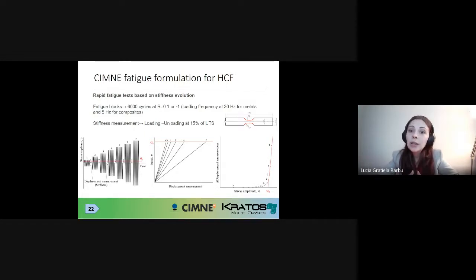And after each of these loading blocks, they do a loading and unloading of that specific specimen at 15% of the ultimate tensile strength. This is done to detect the change in stiffness inside the material. You can see here, for instance, that the loading history for this type of test has a progressively higher stress amplitude applied on the specimen. As you finish a block and then check this change in the stiffness, you can see here that the displacement measurement varies after each load. So if you quantify this change in the displacement measurement and plot it against the stress amplitude, you can detect the fatigue limit of this specific material.